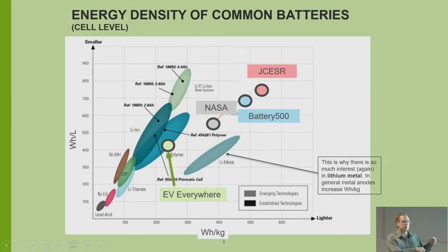Then you hear the term lithium metal batteries. So that's where the negative electrode is actually lithium metal. One thing you notice is you get a lot of energy per weight, but not really much gains, or really no gains, per volume. And that's because lithium is very low density. Its specific gravity is 0.5, so volume for volume, it's half the weight of water. So when you throw a lithium piece on water, it floats. And well, it violently reacts, but it floats.